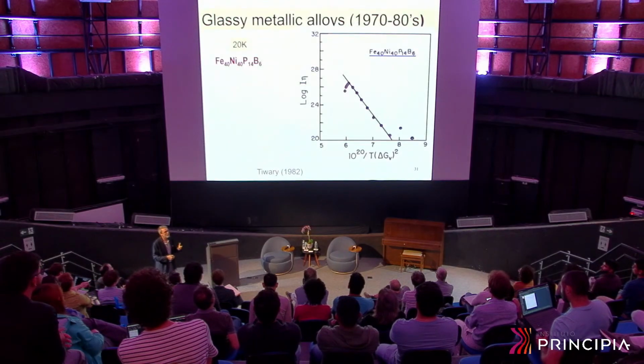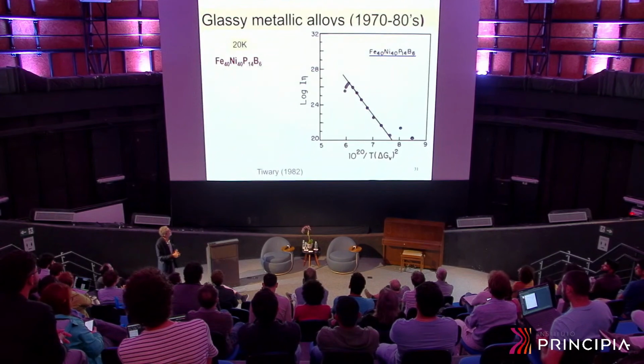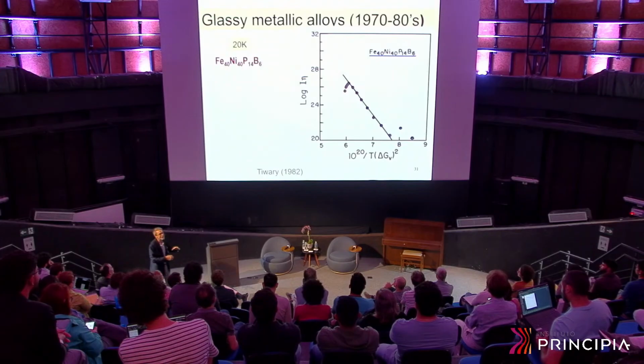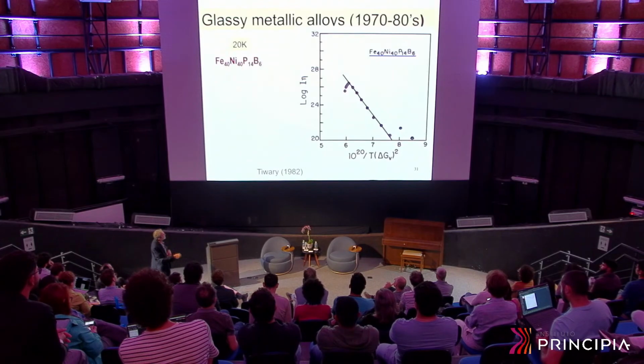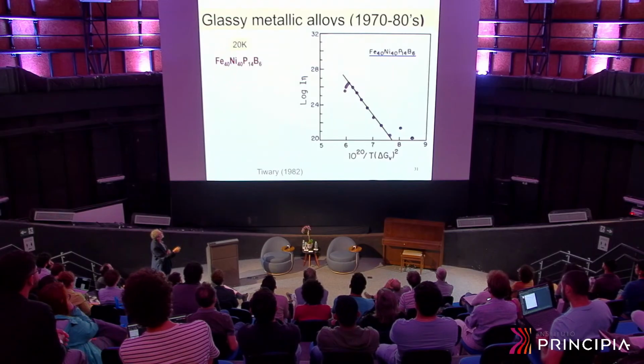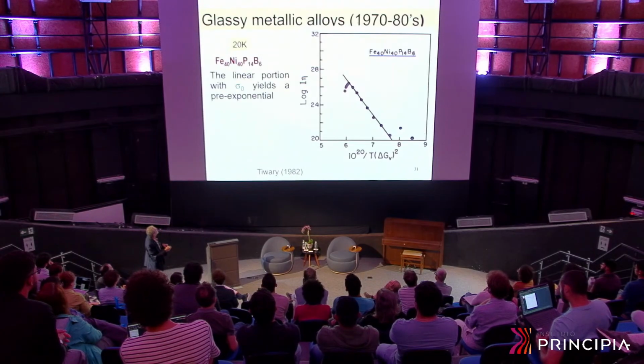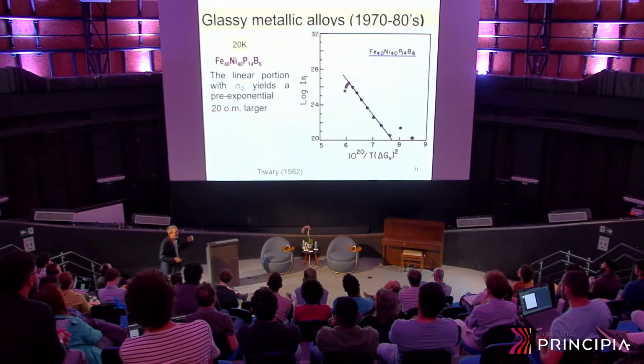Metallic glasses were discovered in the 70s. So the first people to measure, forget the noise here, get the straight line, extrapolate it, and compare the theoretical and experimental values in this metallic glass. 20 orders of magnitude.